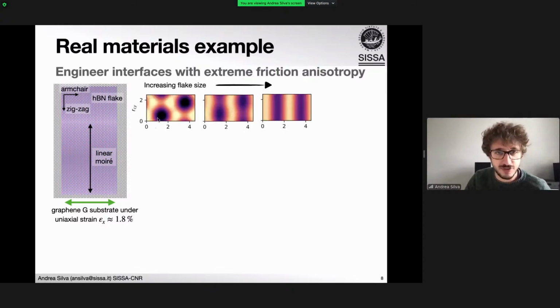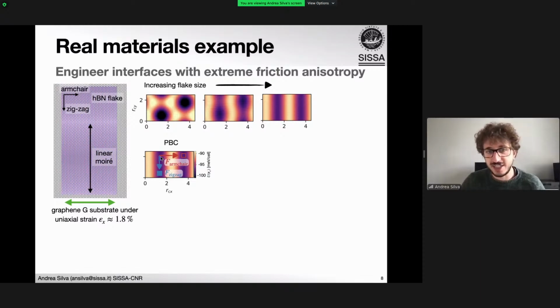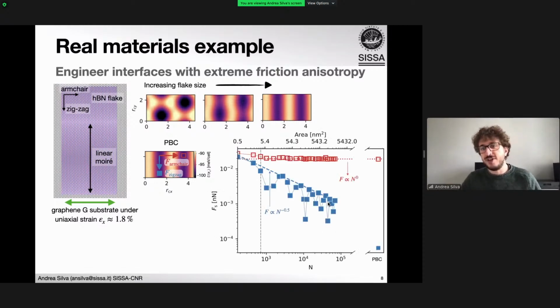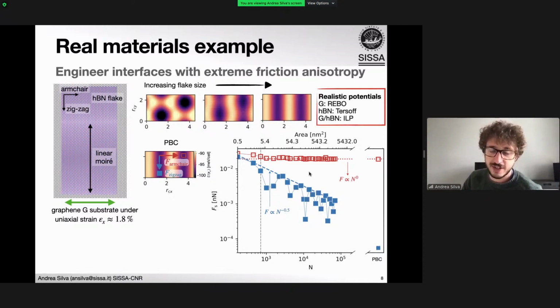The system goes from the usual hexagonal moiré pattern, and as the size grows, it develops this valley, up to the infinite limit system where you have perfect valleys in between them. Then we can probe the friction sliding perpendicular to this valley or parallel to them. We find a scaling of the friction in the two directions which is very much in agreement with what the theory expects. The situation here is of course more complicated because we use realistic potentials, not some approximated Gaussian.